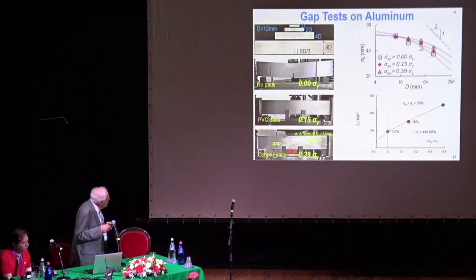As you increase the crack parallel stress, this is changing, and this is the combined effect of the micrometer-wide process zone width and the millimeter-scale yielding zone. And to sort it out, you need to do further analysis, which I'm doing now, or further testing at a smaller scale. If we plot this in this regression plot,